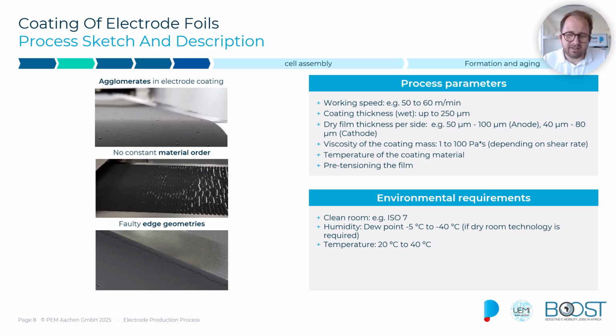So here you get a good insight into potential errors you can create within your coating process. You see in the first overview potential agglomerates which could still be visible in the slurry after the coating process. Also, sometimes you leave holes in the coating, so there's no constant material flow in the drying or coating process, and of course you want to avoid that. Also, the edges of the coating can be very faulty, more like waves or having holes, or very uneven. In all this you typically want to control with a camera vision process, while also keeping up with the high speed of coating which is necessary to meet the production rates in your production process.